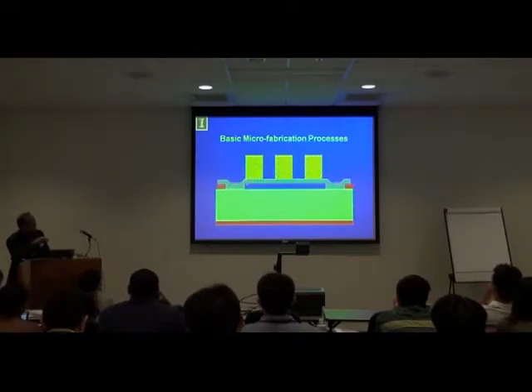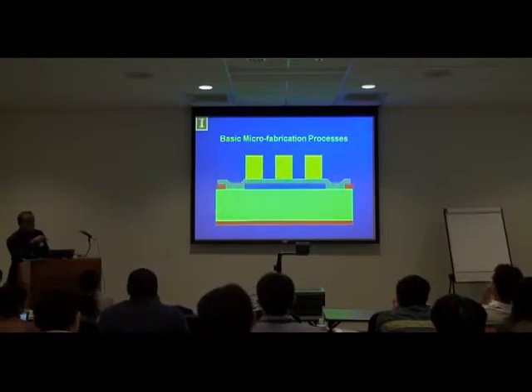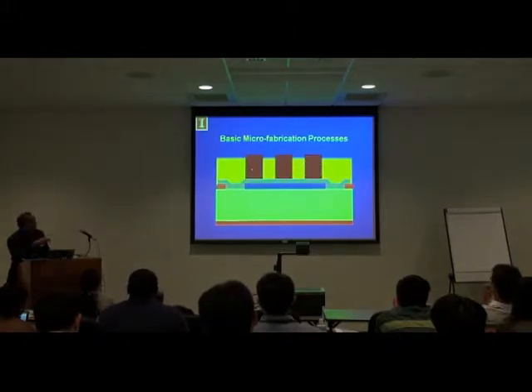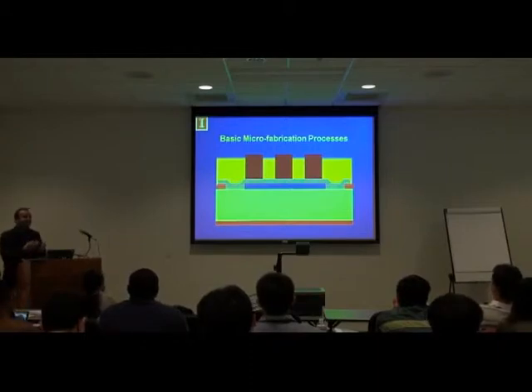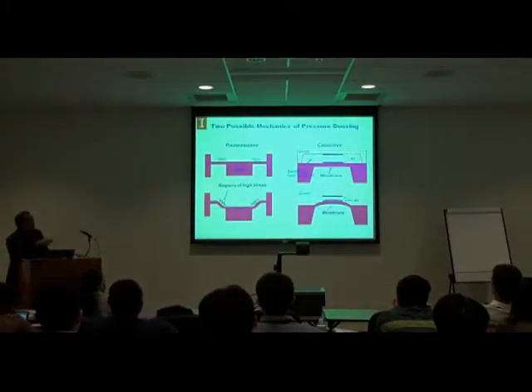Then you can use this metal and then deposit a photoresist mask shown here and actually form these regions, and then use the metal as a mask for electroplating and plate gold, for example. The color didn't show, right? But you can plate gold, for example, and remove the photoresist now. So now you end up with these regions, which are these gold structures on a suspended membrane. So you can do lots of things in terms of fabrication and make these three-dimensional structures. Okay. So let me give you some examples of what you could do with things like this.